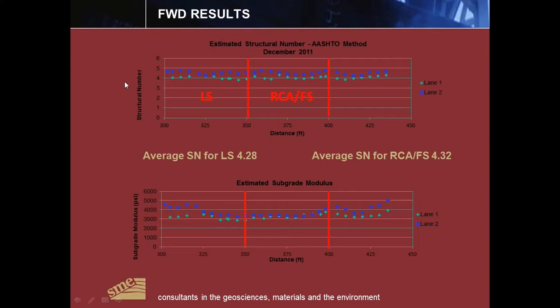This presents the data after our test in December of 2011. This data is not temperature corrected to 70 degrees. It's the original temperatures that the pavement was at the time of the test. You can see the upper number here plots lane 1 and lane 2. You can typically see on these curves that lane 1 numbers are lower than the lane 2 numbers. We think this is due to the proximity to the edge of the pavement and also to the trench drain that runs along that edge.